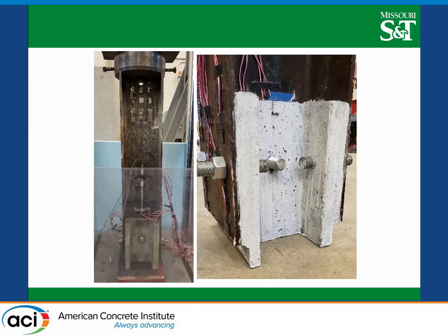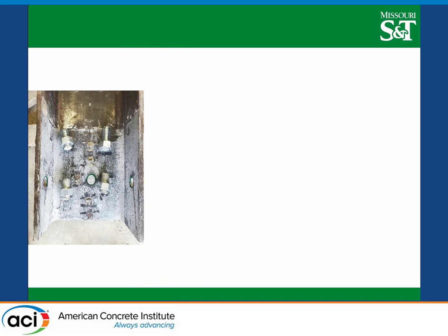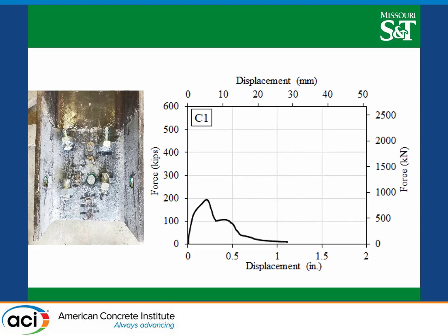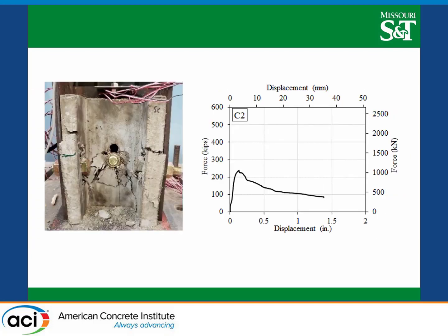And then, as we did with the wrapping, we start from scratch. We also have different bolt sizes, bolt distribution, diameters, and we start looking, okay, if we push this and we have the gap over here, how much force you can transfer. As you would expect, the first mode of failure would be, if you don't have enough bolts, or the diameter of the bolts is not enough, you shear off the bolts. And this is the force versus displacement that we get. Very typical for this sort of failure.